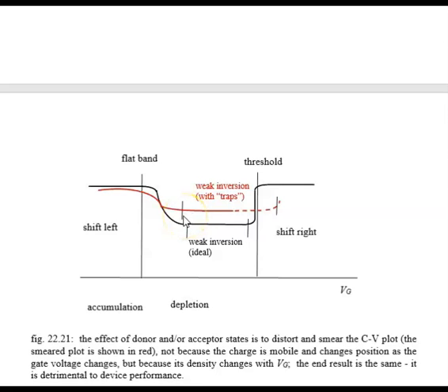Actually, I'm not even quite sure whether I have this in my notes, but you can do some calculations here. They're a bit rough, perhaps, but this is the region that is bad. This is the weak inversion region. This is the region we want to make as small as possible. This point, for example, would be intrinsic, close to or at threshold. So the weak inversion region, if we have no interface traps, would be the points from here to here.